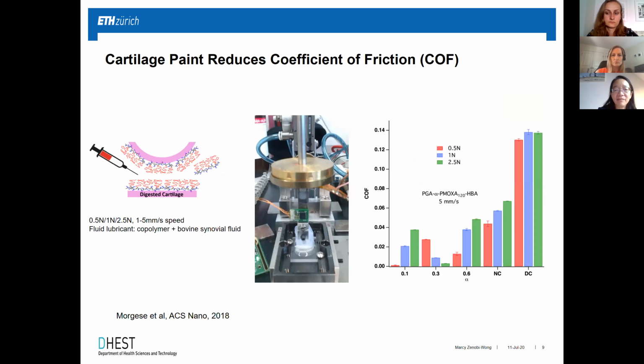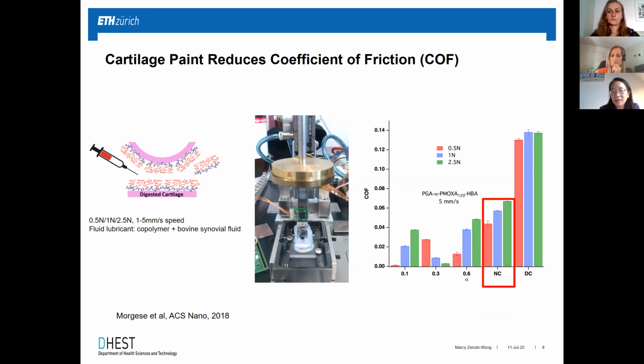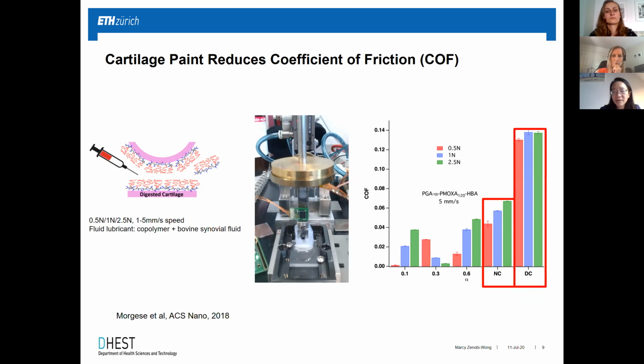And so I wanted to show you some in vitro results that Julia obtained, looking exactly at the coefficient of friction of different surfaces. So the machine on the right is measuring this coefficient of friction. And what Julia did is to measure the coefficient of native cartilage. This is this NC. And you can see the values are between 0.04 and 0.08. So it's a very low, slippery surface, as it should be. She then tried to simulate this disease state by just digesting the surface. She took healthy cartilage and digested the surface and found that the coefficient of friction then doubled.